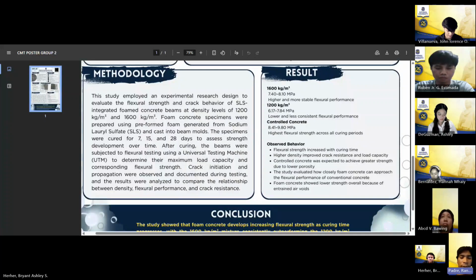Thank you, Mr. Villanueva, for reporting the density levels. So, for methodology, this study employed an experimental research design to evaluate the flexural strength and crack behavior of SLS integrated foam concrete beams at density levels of 1,200 kilograms per cubic meter and 1,600 kilograms per cubic meter. Foam concrete specimens were prepared using preformed foam generated from sodium lauryl sulfate, or SLS, and cast into beam molds. The specimens were cured for 7, 14, and 28 days to assess the strength development over time.